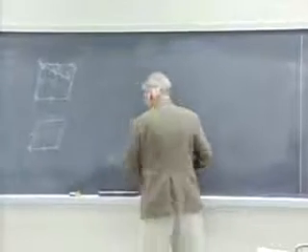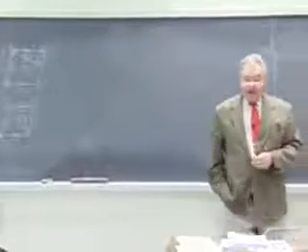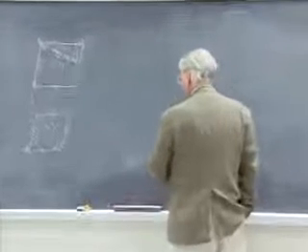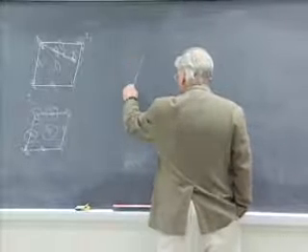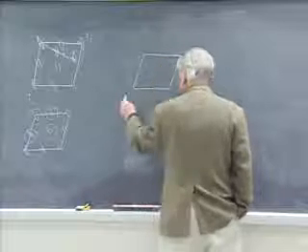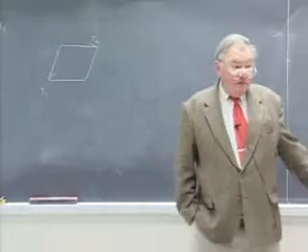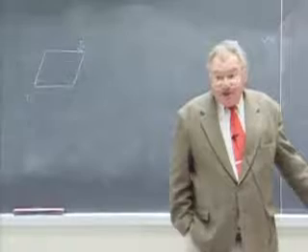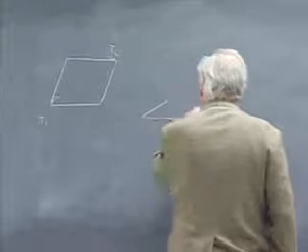So those are the 4 ways we can combine an oblique net that contains a twofold axis in such a way that the lattice points in the existing twofold axes remain invariant and are not moved into locations that create new twofold axes. Okay, so let's back off a little bit and start with plane group P1, no symmetry at all. So that this is T1 and T2. If there's no symmetry whatsoever in the base of the cell, we're free to pick the third translation in any orientation that we choose. So trying to sketch it in 3 dimensions.